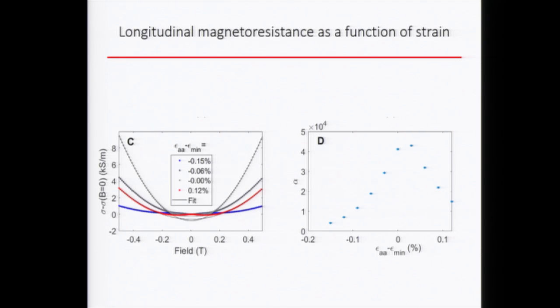So this is just some quantitative fitting of the magnetoconductance. Now you have a positive magnetoconductance, and from the B squared dependence, you can extract a chirality or helicity relaxation rate, which in theory should diverge as you get close to the gap equal to 0 case. So this fitting also matches the picture.